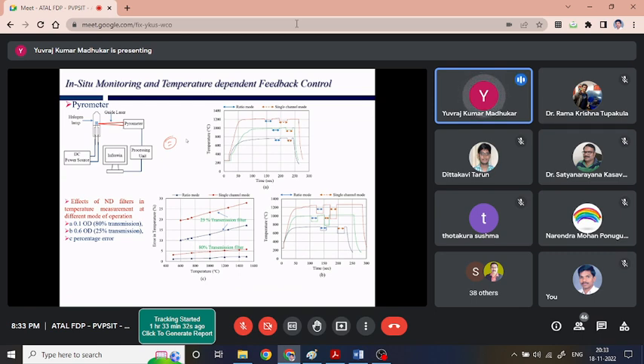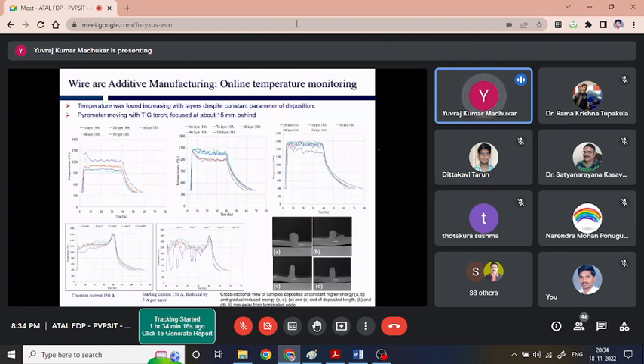So luckily we got this system, and we tried to see how much error we are getting. We could see, with respect to the different parameters, that in case of a single channel operation, it gives nearly 20 to 30% error in temperature measurement. Now this temperature error of nearly 20 to 30% is significantly high when we talk about a feedback-based control system. So yes, it is costly. However, it gives the lesser error. So it is best suited for additive manufacturing and for the monitoring and control system.